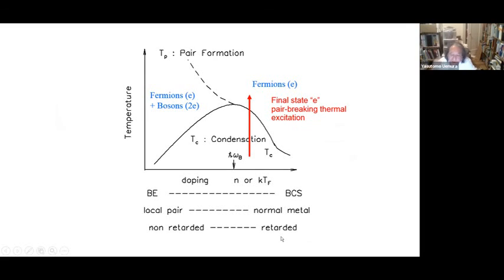This magnetic resonance mode is well known to be a d-wave superconductor response in the case of the optimal and overdoped case. In that case, your final state of exciting the condensate is, you excite bosons, but it is becoming E. And so this is a pair-breaking excitation. This is exactly what the usual people would love to say about d-wave. However, if we consider the underdoped side, rather deep underdoped side, most of your normal state is 2E. And so then you excite this boson to another boson in the normal state. That should be the process to determine thermodynamically the Tc. And so for this pair non-breaking excitation, I think this resonance mode is a very good candidate.